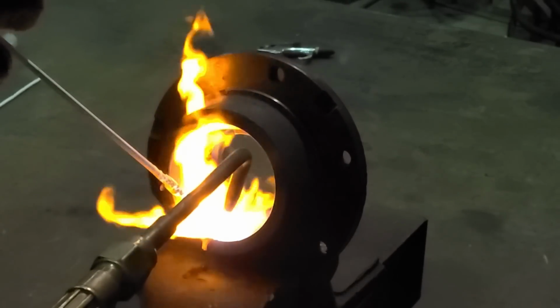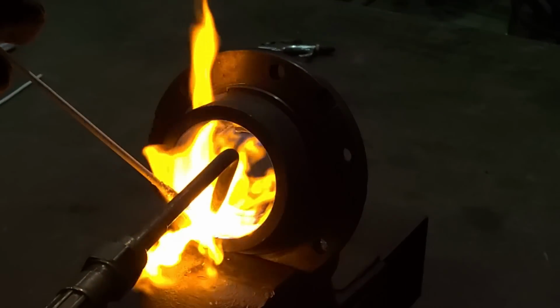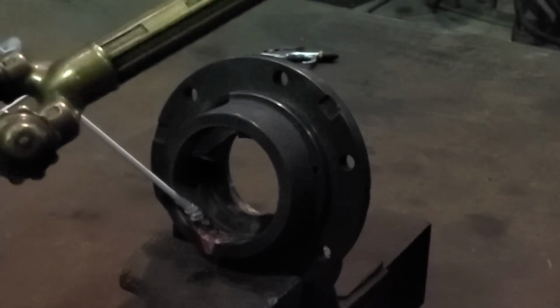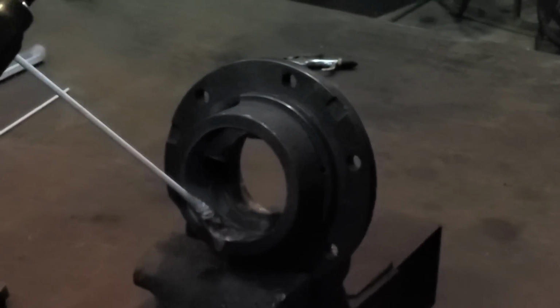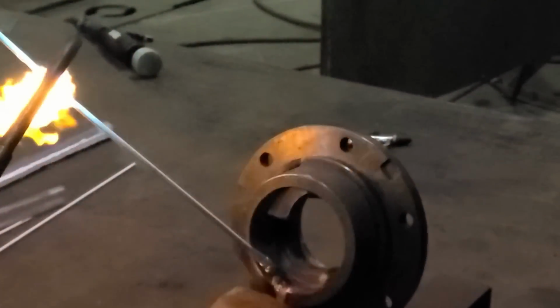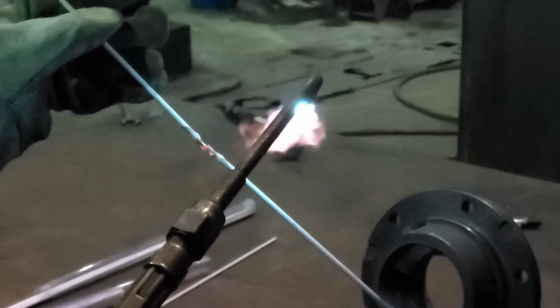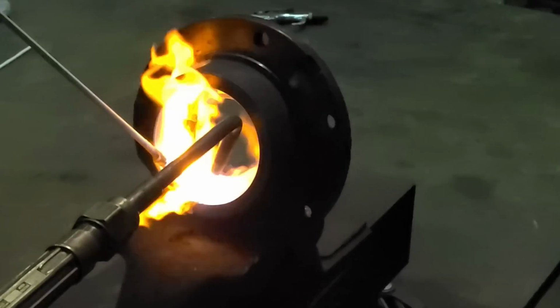Now, if I come in real close to the bronze or brass, whichever we want to call it this minute, I can melt this by getting the torch real close to it, but if I do that too much, what I will do instead of doing a nice braze is I will just burn up the material. And this is something that you do so that you don't have all those little wasted pieces of rod. You extend a piece onto it. And brazing is definitely an art more so than just a quick instruction. You have to practice it.